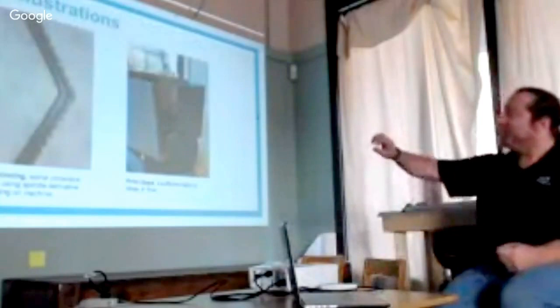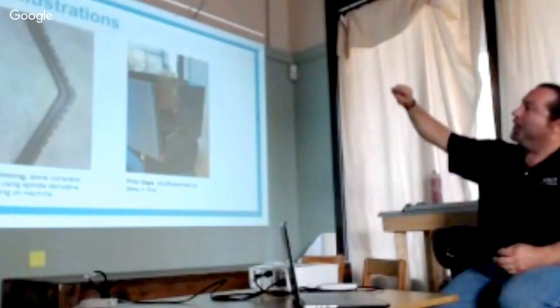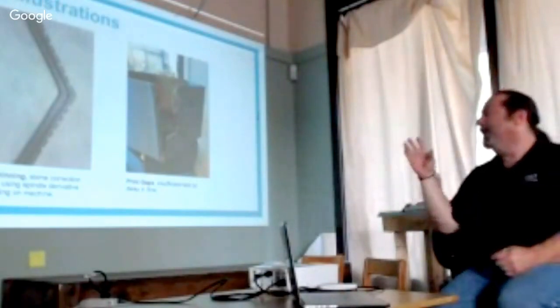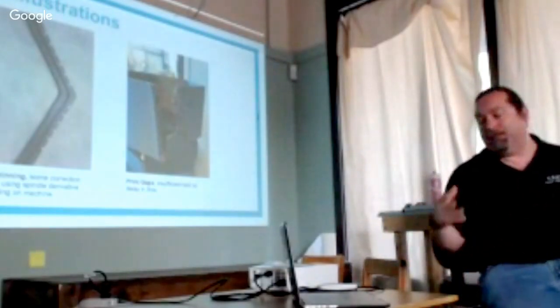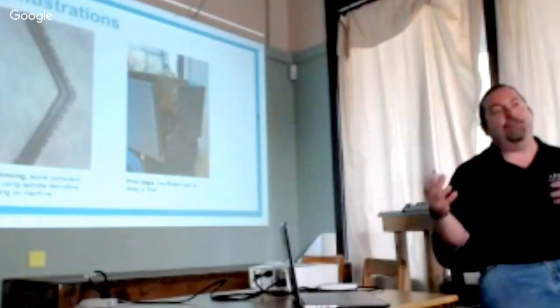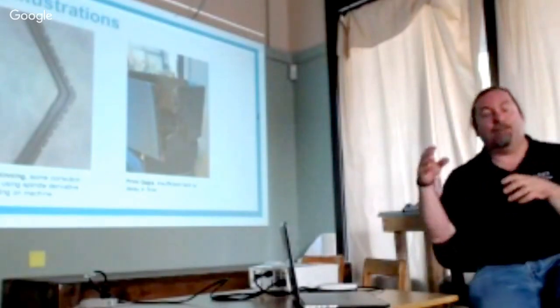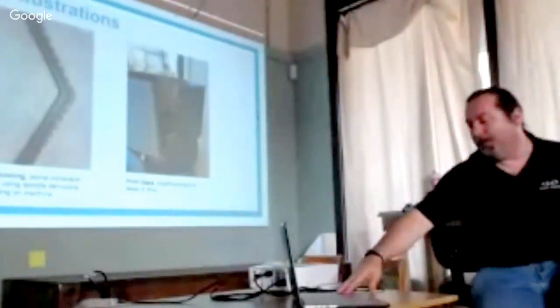The bead thinning, it's kind of hard to see in the slide, but when you measure this, you can see how as it slows down going into a corner, the bead tends to thicken, and then as it accelerates out of the corner, it thins again. There are some settings in the machine. Spindle derivative gain is sort of what it's called, and you can tweak that a little bit to try to calibrate it. They're trying to add to the machine to make it actually self-calibrate by measuring this width, but that's not implemented yet.